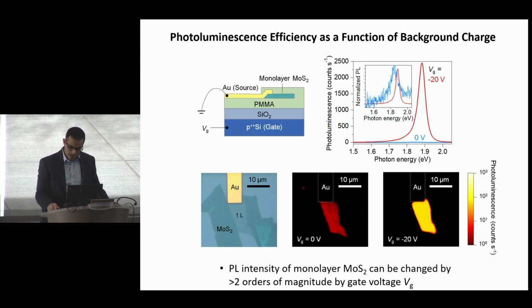So then the question was, what's the mechanism for TFSI enhancing the quantum yield? We knew that TFSI is a Lewis acid. Lewis acids are molecules that withdraw electrons. So this goes back to the charge transfer. So to validate the mechanism, we built devices where we were doing gated photoluminescence studies. So we were measuring photoluminescence of a monolayer while applying a gate voltage. And you can clearly see that the photoluminescence strongly depends on the gate voltage.